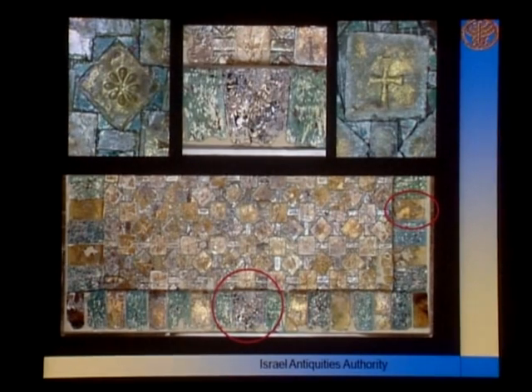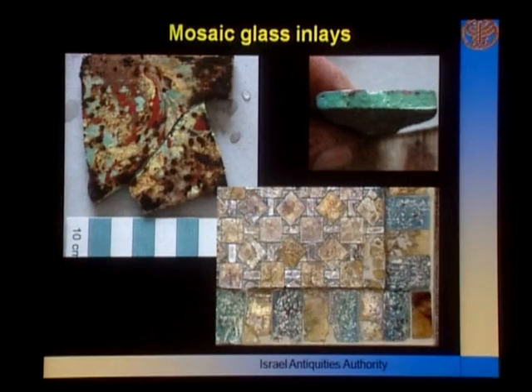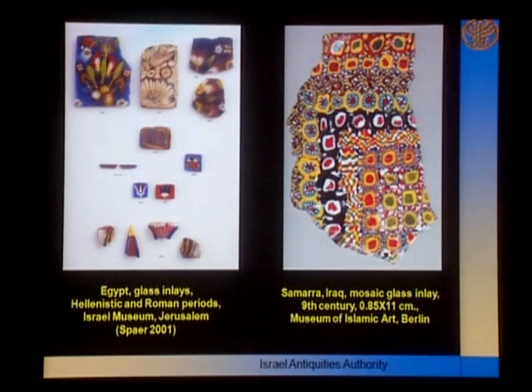A closer look at the mosaic glass tiles in the frame and the panel reveals they are made of colored glass in combinations of opaque green, red, yellow, and grayish blue. They are covered with dark black patches of corrosion and a thick layer of weathering. Some are severely pitted. We are familiar with the role of mosaic glass inlays in the Hellenistic and Roman worlds. However, the mosaic glass inlays from Caesarea are the first dated to the Byzantine period and may represent the missing link to mosaic glass inlays in early Islamic architecture.